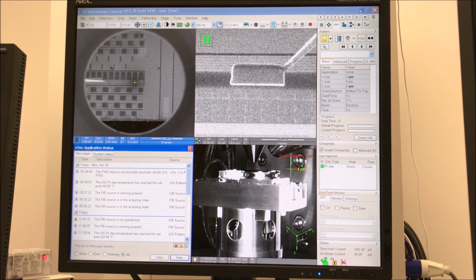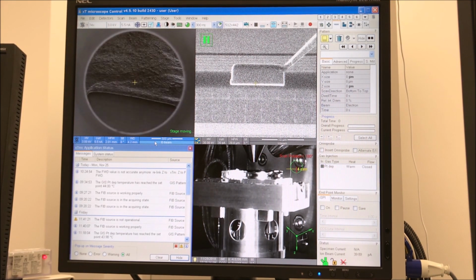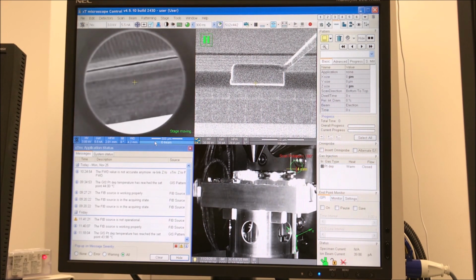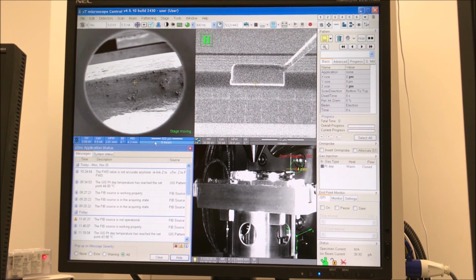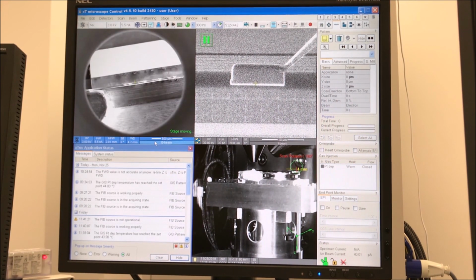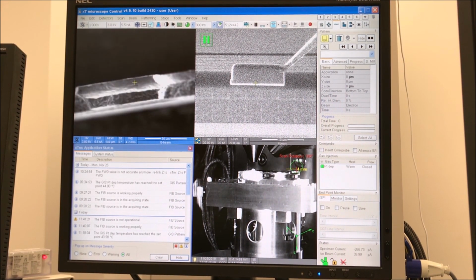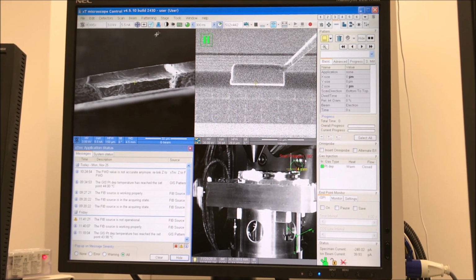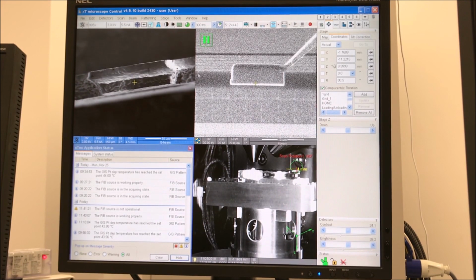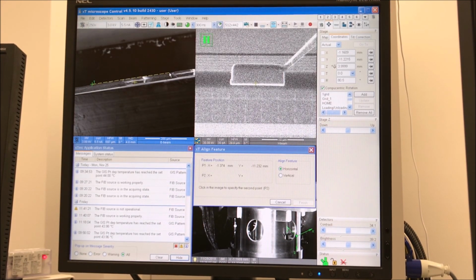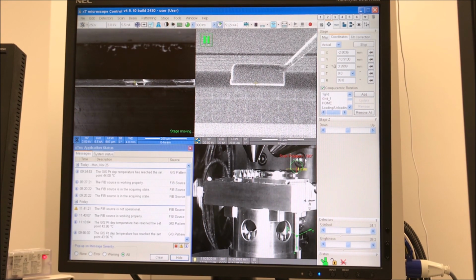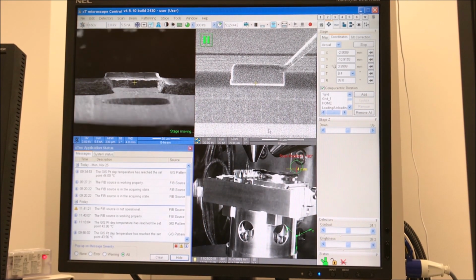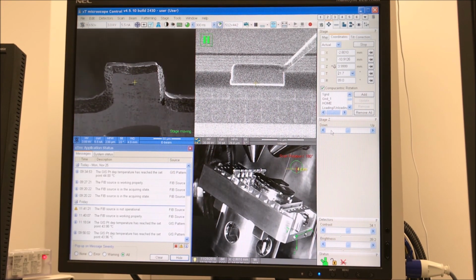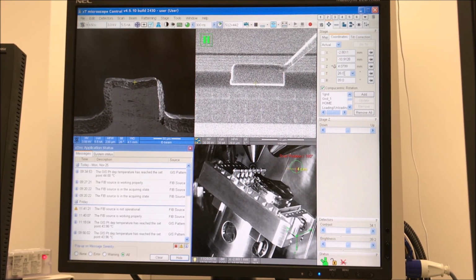And so once the omniprobe has been retracted, I can navigate over to the grid, and we can set that up for attaching the lamella. So now I've moved over to the TEM grid holder, and I'm going to look for the clip that has the grid in it, which is this one, and I'm now going to set the grid up to be ready for lamella attachment. So focus on it, link Z with the working distance, and then you can see the grid is rotated, so I'm going to rotate the stage to align it, and then I'm going to set eccentric height in the middle of the post, which has a little bit of a notch in it.